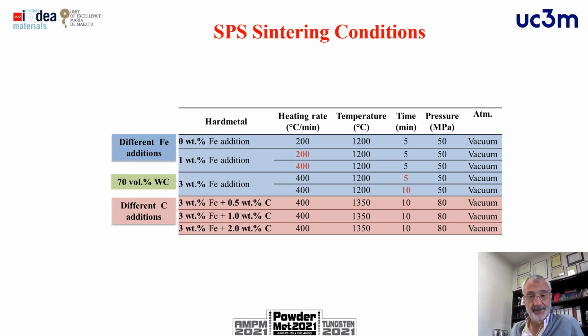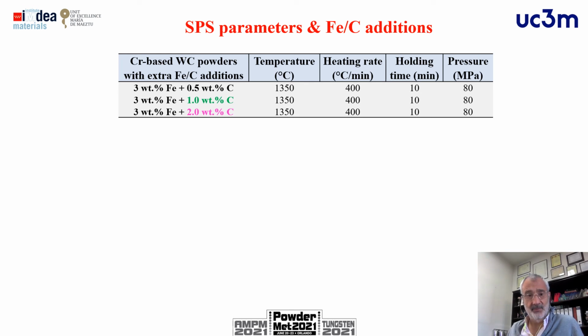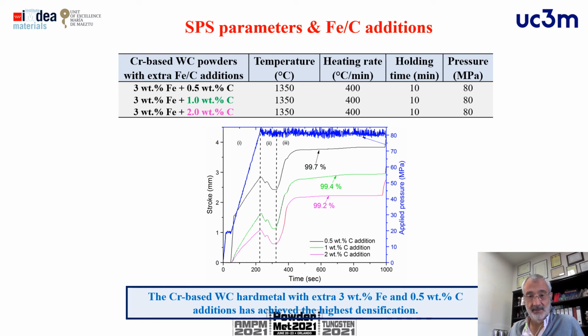As you see here, we have changed the heating rates. We can even test different temperatures, 1200 or 1350 centigrade degrees, and different times and different pressures. At the end, we have selected for our best combination of material, which is 3% of iron with 0.5, 1 or 2% of carbon, the highest temperature, the heating rate of 400 degrees per minute, for a holding time of 10 minutes and a pressure of 80 megapascals. This holding time with this high heating rate allows us to get a good densification.